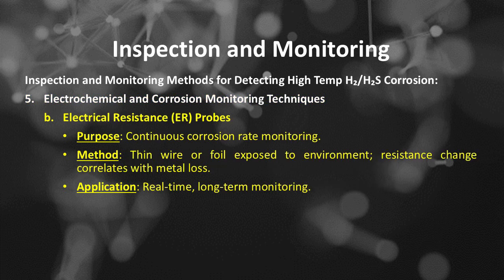Number B is using electrical resistance, or ER, probes. This is purposed for continuous corrosion rate monitoring. The method of using ER probes is a thin wire or foil exposed to the environment. Resistance change correlates with metal loss. The application of using ER probes is real-time, long-term monitoring.